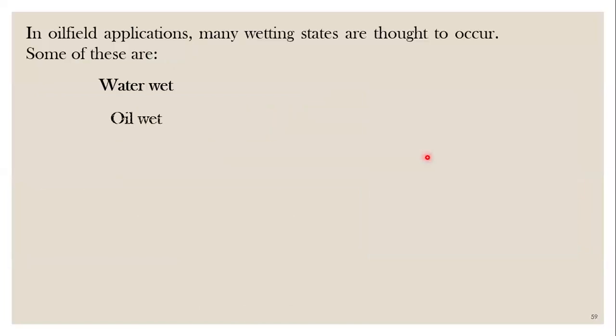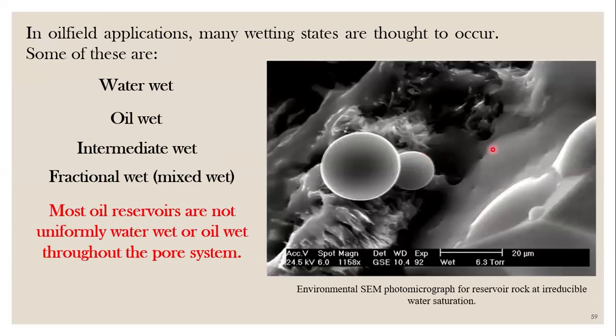There is another type called mixed wet, which means that some part, if you look here, this is clay, and this is silica. And this is a drop of water. You will find that the drop of water is actually spreading over the silica. So if we measure the contact angle between the silica and the oil here, you will find it to be water wet. But on the clay here, the water is like a ball. So it is oil wet.